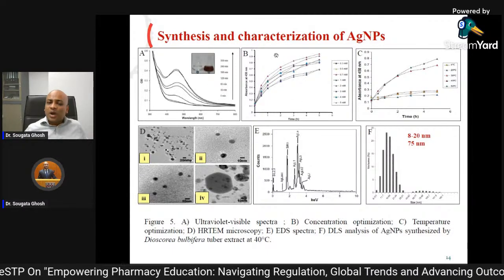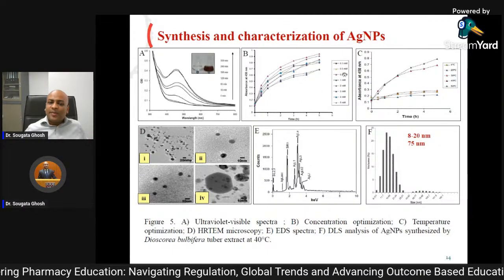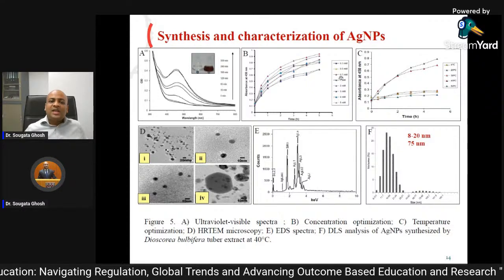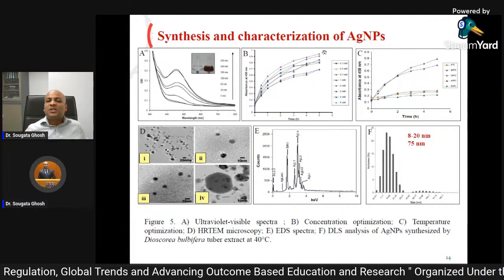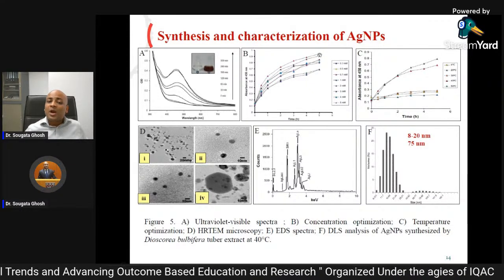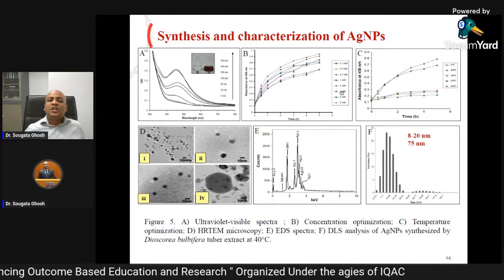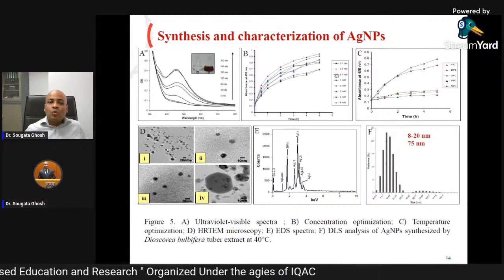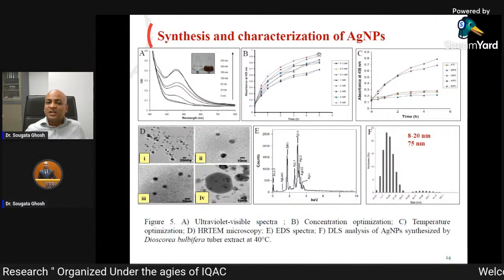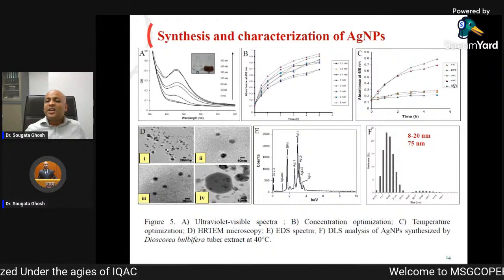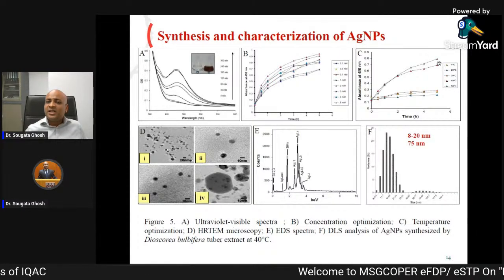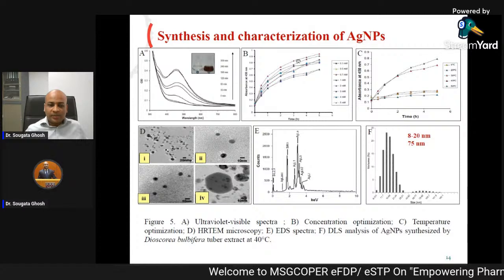Here we tried to optimize the parameters, and we found that 0.7 millimolar was best. In gold, it was 1 millimolar, but for silver, 0.7 millimolar was best in synthesizing the silver nanoparticle. 50 degrees was best. It was showing highest nanoparticle formation.